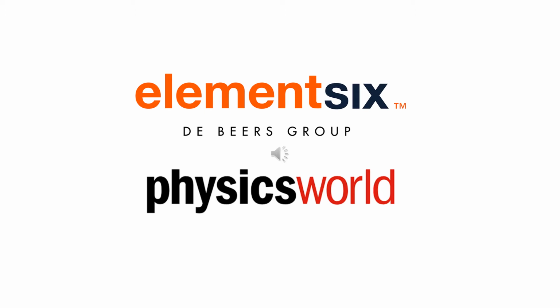That nitrogen vacancy center, once formed, is very stable. You have to heat the diamond to more than 1800 degrees C to break it down. The vacancies might be introduced through the growth process and the nitrogen vacancy grown in, or more typically, after we've grown the diamond with nitrogen, we will add vacancies by hitting the diamond with high energy radiation to create those gaps. And those gaps, under annealing, will migrate to form the nitrogen vacancy center.